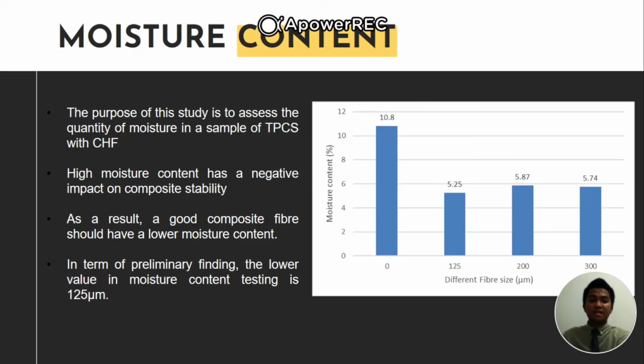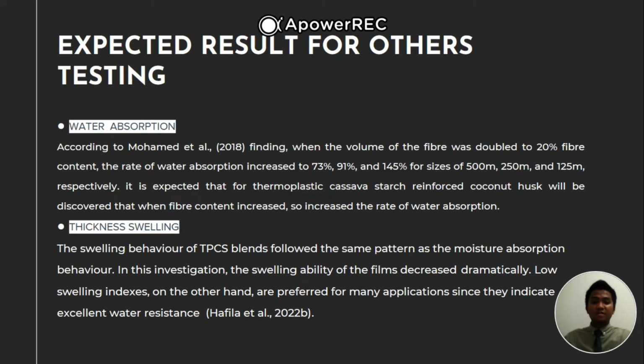For moisture content, the purpose of this test is to assess the quantity of moisture in a sample of TPCS with coconut husk fiber. High moisture content has a negative impact on composite stability. As a result, a good composite fiber should have a lower moisture content. In terms of a preliminary finding, the lower value in moisture content testing is 125 micrometer. Expected results for the other testing.